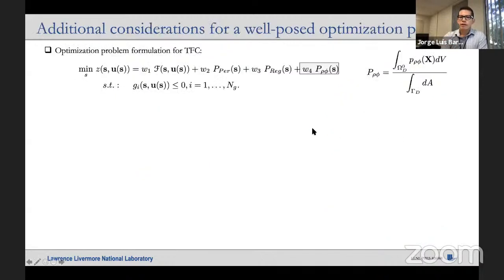And where do we introduce this penalty for the two-field coupling? Well, we add it as another term in our objective. So this is a typical optimization problem formulation that we use. F here in the objective is your quantity of interest, what you're interested in: strength, energy, mass, et cetera. Then typically we include these two terms, the perimeter and the regularization terms. The perimeter penalty is meant to get smooth converged designs in your level set problem, to avoid the wiggly behavior of your optimal geometries. And the regularization is to promote the smooth evolution of your optimization problem and have a stable overall process.